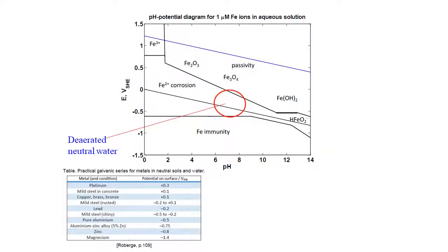On the iron diagram, we should look at this because this is important for steel, obviously the most important metal for you to understand. Unfortunately, iron is a bit more complicated than any of the other systems we've looked at so far. That's because iron is one of the transition metals which has higher solid oxides. And also because it has a lot of different things it can do in solution. You can have Fe2+ or 3+ ions and a few other ones, and the ions in solution can actually go on and do some acid-base conversions as well. But not worrying too much about that.